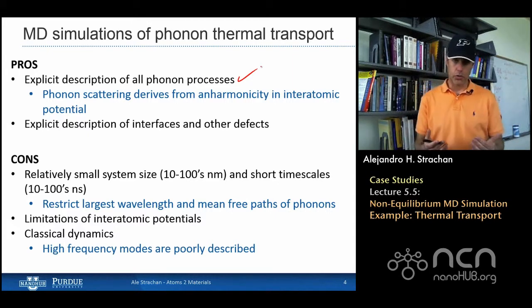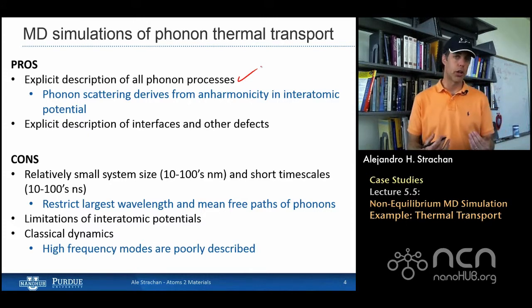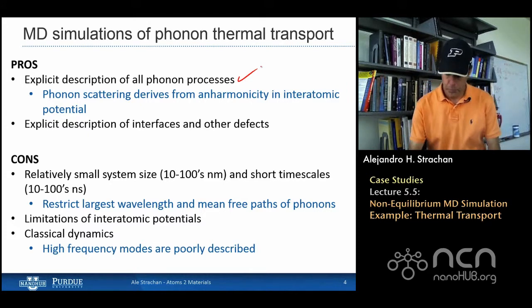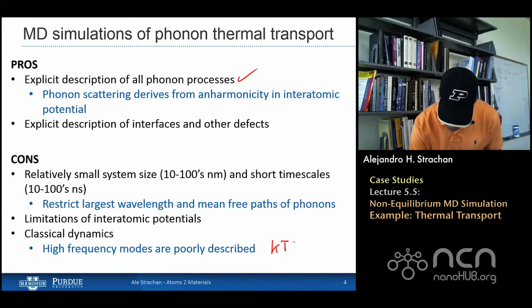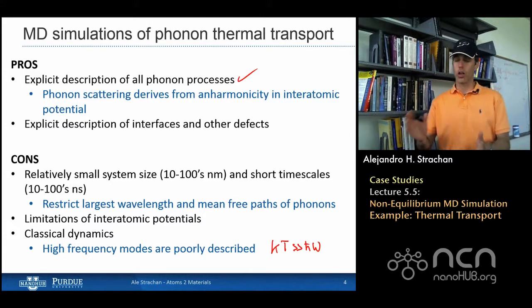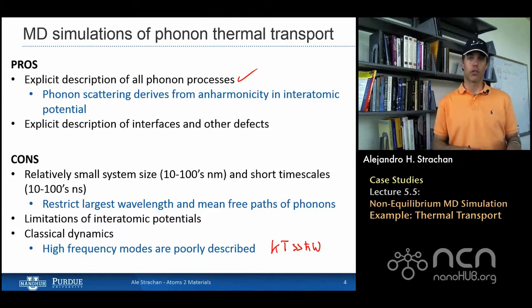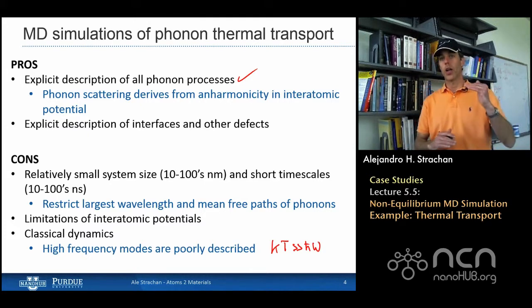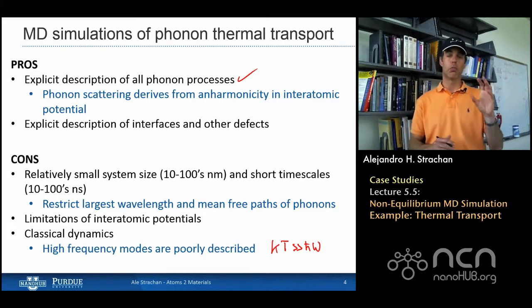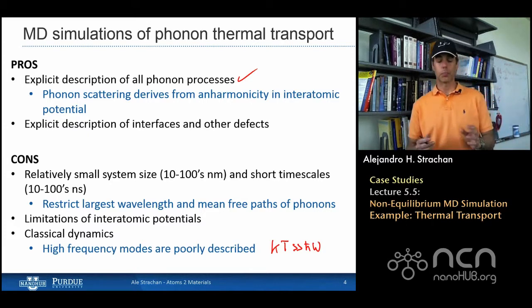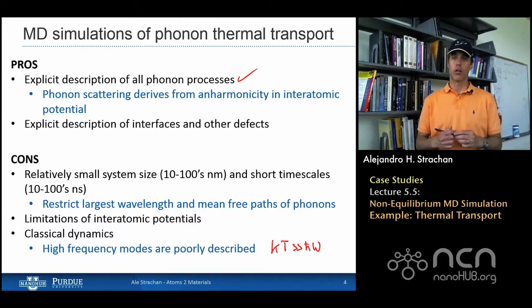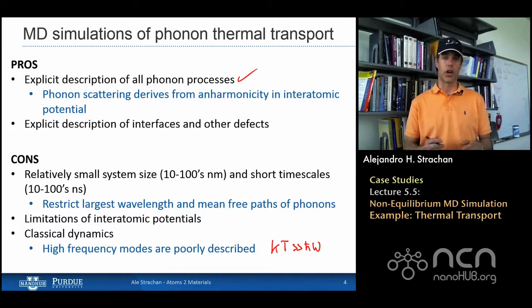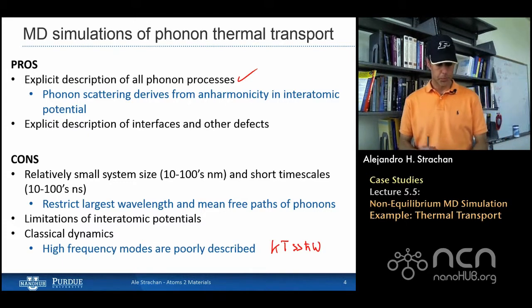And we know that our description breaks down at low temperatures or for high frequency modes. Okay, so we are only okay as long as kT is larger compared with h bar omega. Okay, so high frequency modes are not described very accurately. Now, fortunately for us, high frequency modes tend to be optical modes. They tend to have very small group velocities that don't carry a lot of heat. So we can get away with classical mechanics for thermal transport, more than you would imagine at first thought. But for things like carbon nanotubes that have very high frequencies, MDs would not be very accurate.